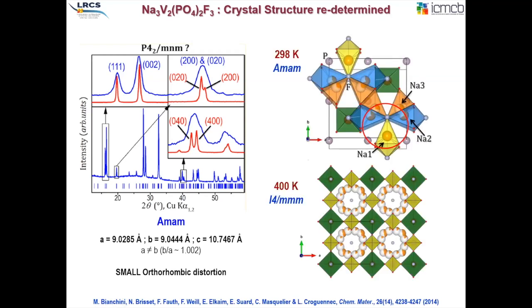This structure is interesting, and this orthorhombic form, due to partial ordering of sodium on the crystallographic sites, can be disordered by slightly increasing the temperature up to 400 K, where the transformation from the orthorhombic space group Amam to the I4/mmm space group occurs, close to 400 K, above 400 K. So this illustrates the very, very fast ion transport of sodium that is completely delocalized in layers perpendicular to the c parameter. That allows very, very fast diffusion of sodium in this compound.